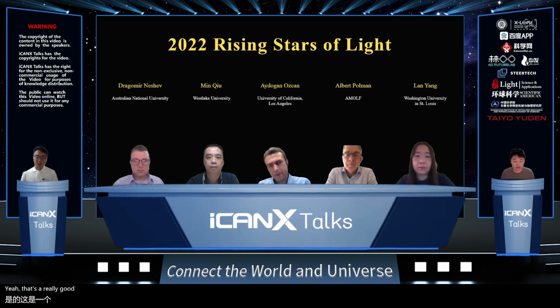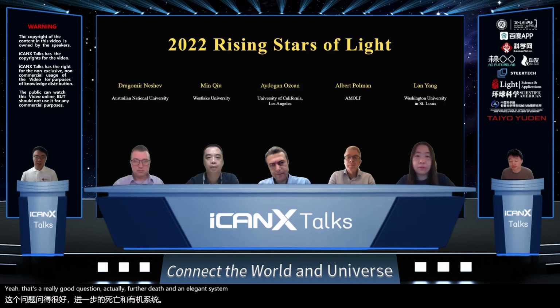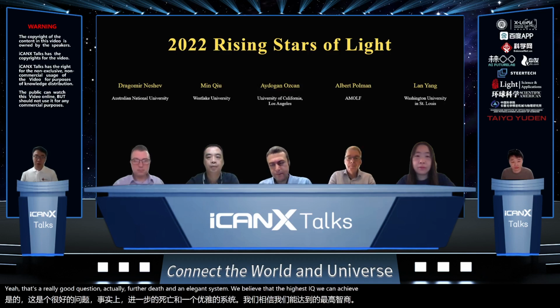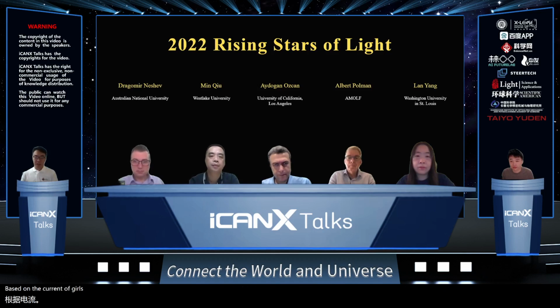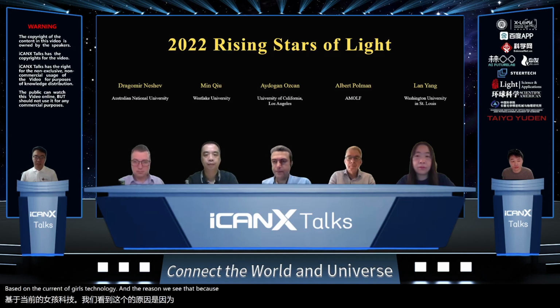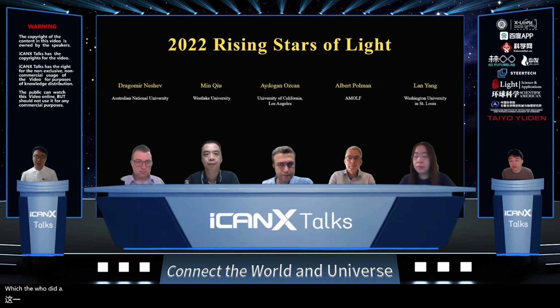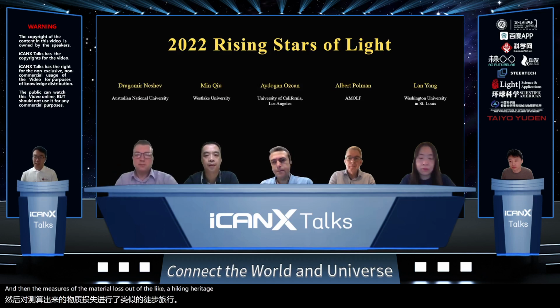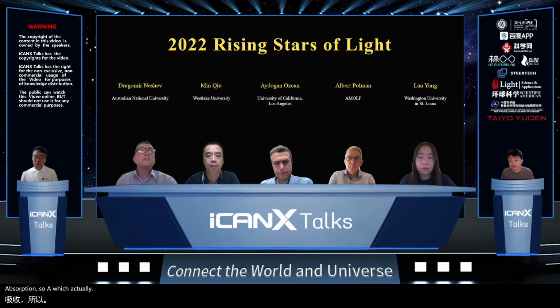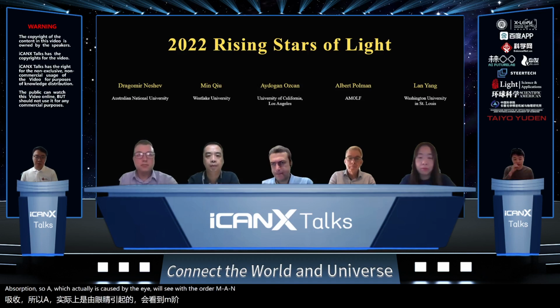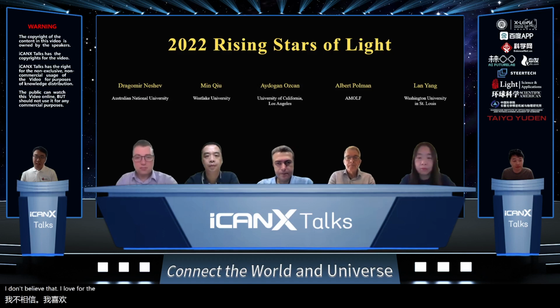Yeah, that's a really good question. Actually, for the GaAs and AlGaAs system, we believe that the highest Q we can achieve is probably at the level of 10 million or 20 million based on the current growth technology. The reason we say that is because we have a collaborator who did a lot of high-Q mirrors using AlGaAs and GaAs crystals. They measured the material loss of those high-Q cavities, and they can extract the loss caused by the absorption, which is caused by the MOCVD or MBE growth. And we believe that for the current growth technology, the limit is probably around 10 to 20 million.